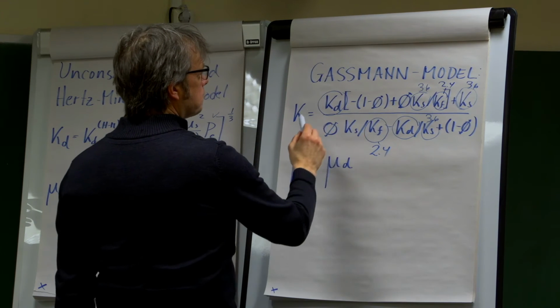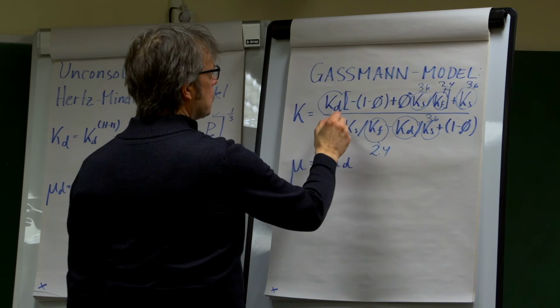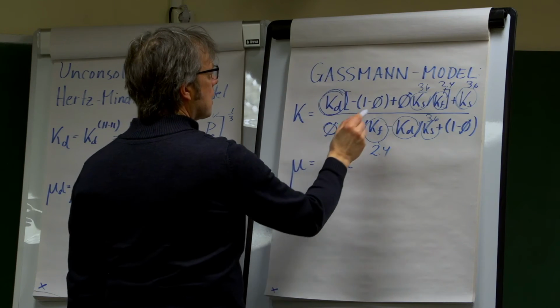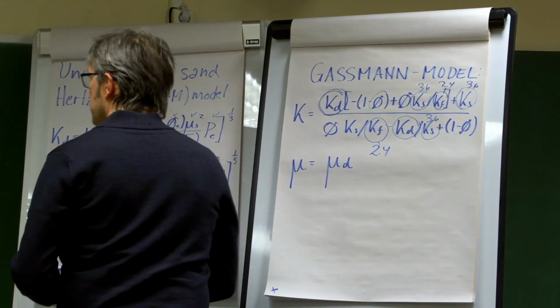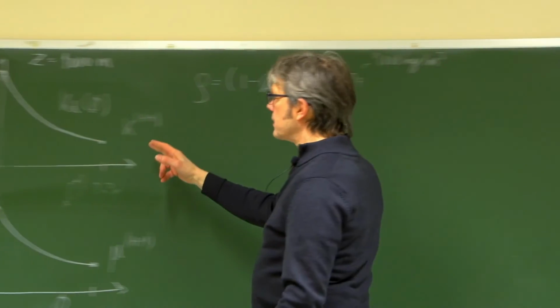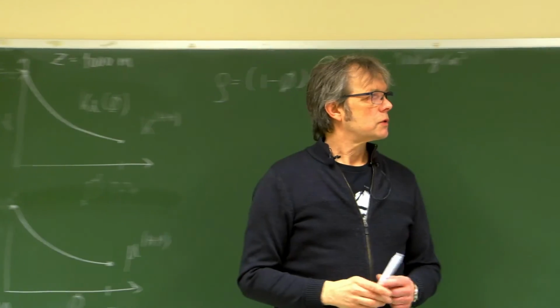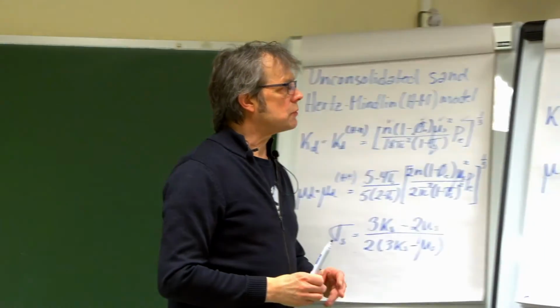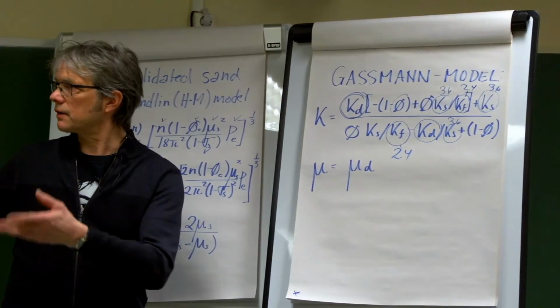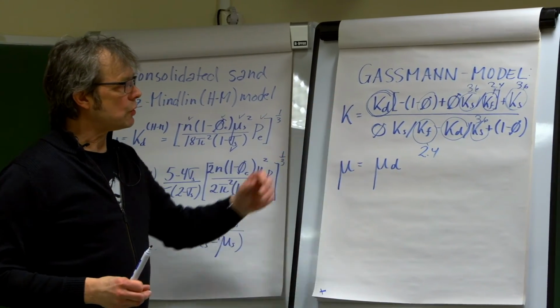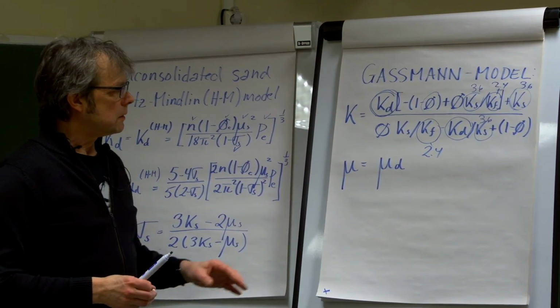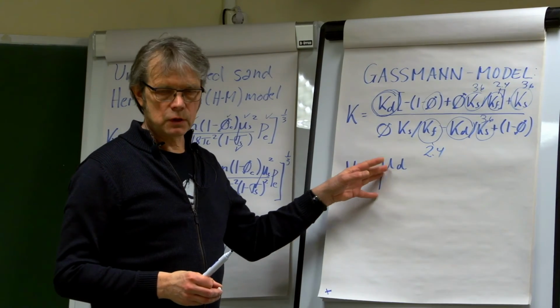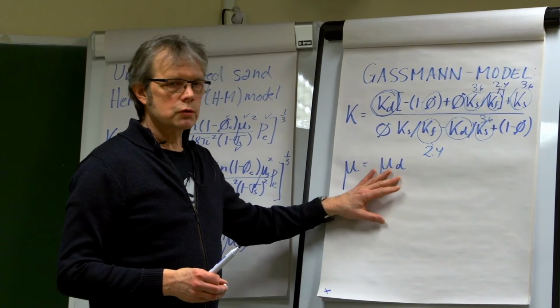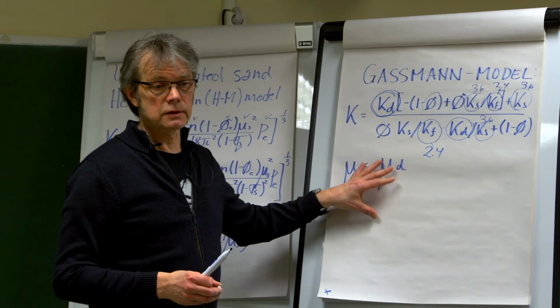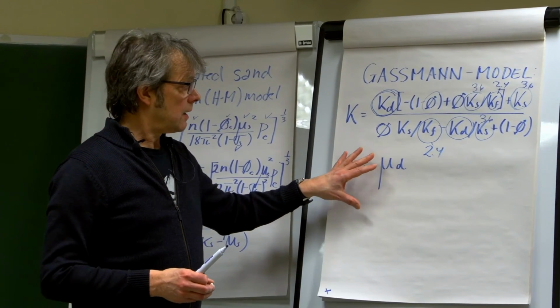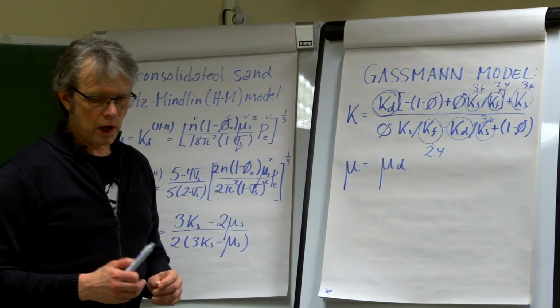And now we can just change the porosity and the dry rock, because we know the correlation between the dry rock and the porosity. We have it here. So now we have all the parameters we need to predict the bulk modulus when we saturate this with, to begin with, water. Shear modulus, well, doesn't care about the fluid inside. That's one of the important issues of the Gassmann equation. So I can just do that.